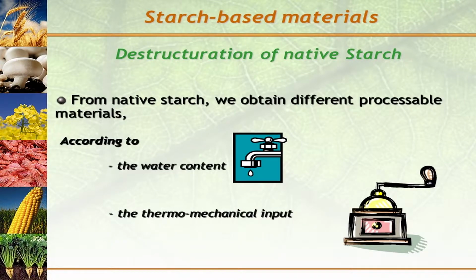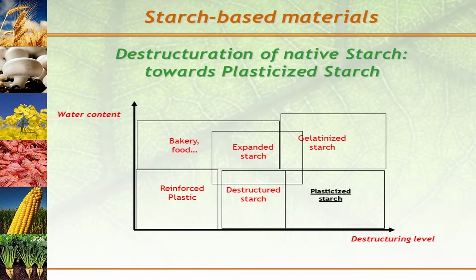So from this granular native starch, we will see that we can obtain different materials depending on the water content and the thermomechanical input we give to destructurate the native starch granules. So it may lead to different types of materials and application depending on the water content and the destructuration level you have. If you have a low destructuration level, low water content, you have almost no transformation of the starch granule. You can use it as a filler to reinforce some plastics.